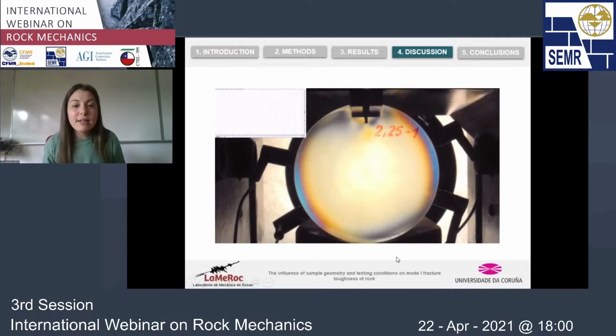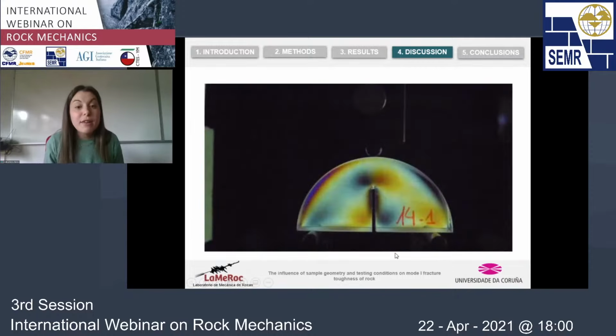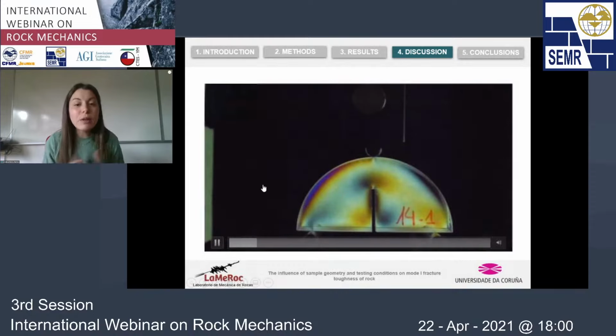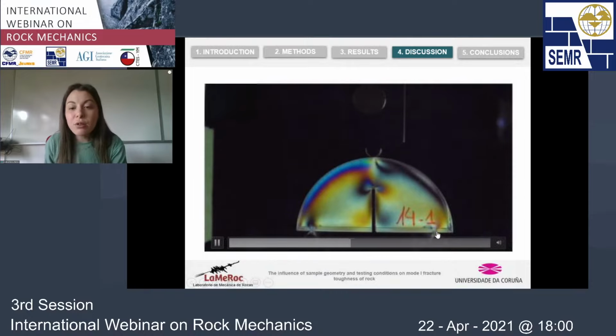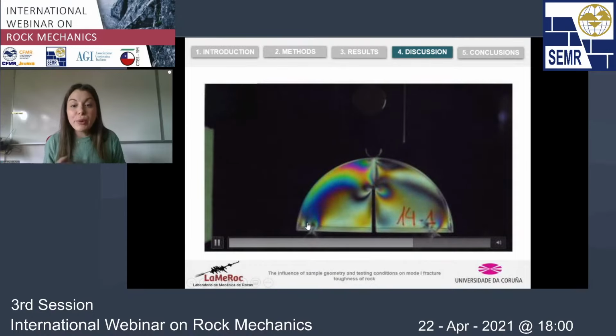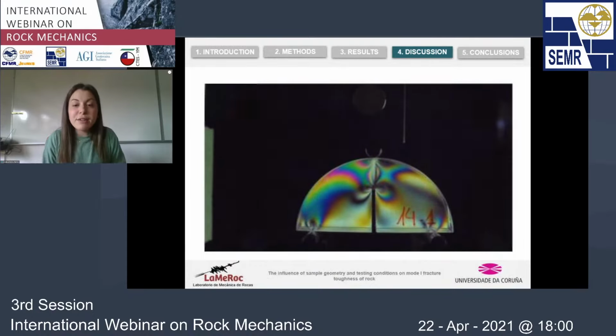And we have done this also for the SCB. In this case, as the load is increasing, we can see that there is a stress concentration here at the notch tip, but there are also huge stress concentrations at the contact with the rollers. So in this case, there is a lot of energy being stored in the sample. When it fails here, what we observe is that all the energy is released suddenly, and we cannot control the propagation of the crack.